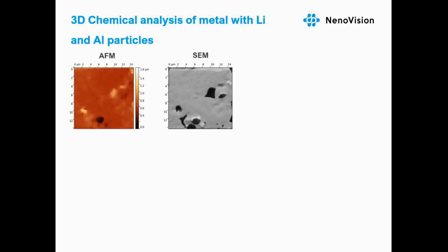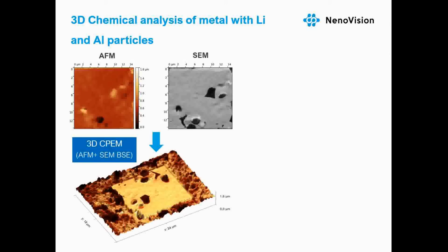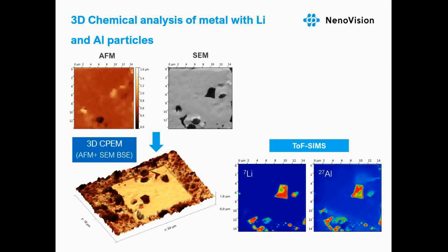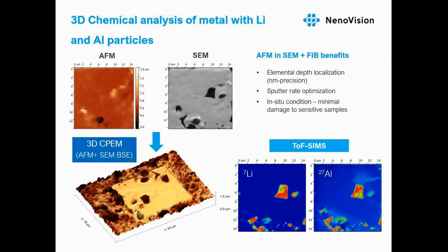In this early stage, it was only possible to correlate the AFM topography with SEM's material contrast to create a comprehensive three-dimensional view of the sputtered crater that can be further compared to the lithium and aluminium distribution provided by TOF-SIMS. In future, further correlation of these techniques will provide detailed depth-correlated three-dimensional elemental distribution. Further advantages of this hybrid technique include the potential for sputter rate optimization, even though this was out of the scope of this application, and additionally, the surface oxidation was avoided thanks to the complete analysis in in-situ conditions.